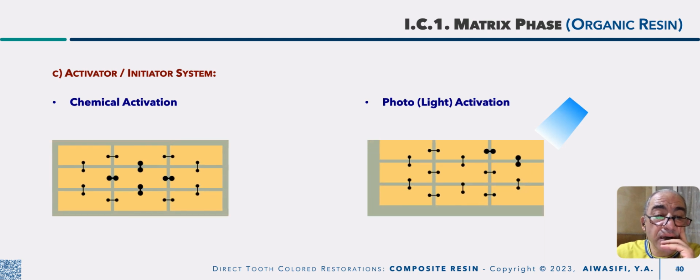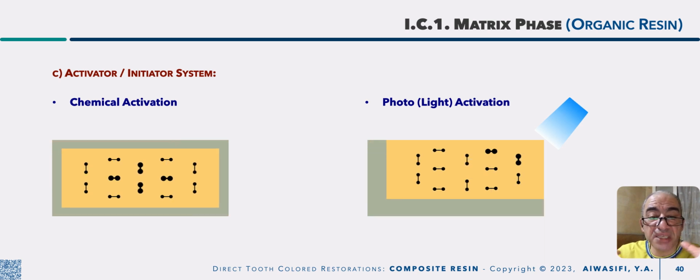That's why chemical cured shrinks towards the center, where it is the site of first initiation and maximum initiation, while for light activated, your composite will shrink towards the light, where the first initiation and the maximum initiation occur. That's why we could use those properties, for chemical and for light activated, to our advantage as clinicians.